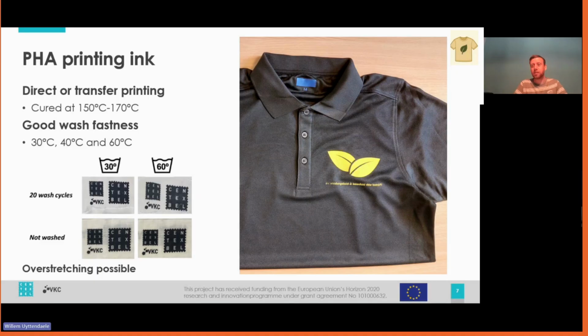So quite a promising material here, especially because these PHA printing inks are fully biodegradable, which means that if they wash off during laundry, they really fully biodegrade in the wastewater and wherever they end up.